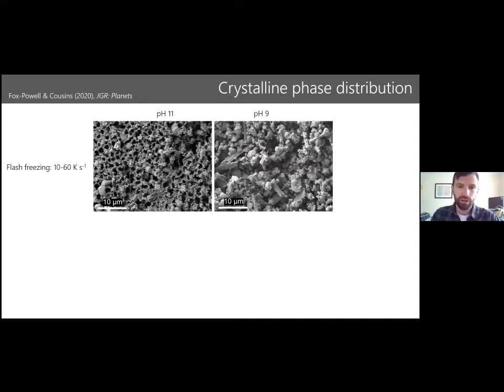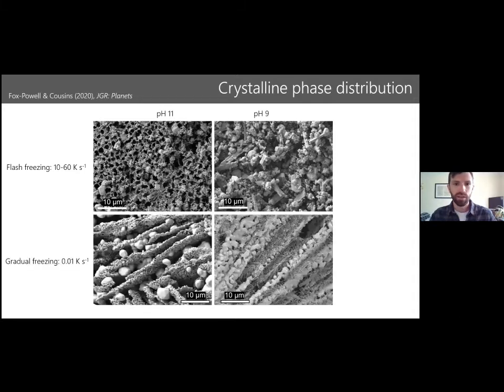So we can look at partitioning within the crystalline material itself. Now we're looking at the sub-brine vein scale. We're looking at the crystalline material partitioning within the brine veins. We did this by extracting this material via full sublimation. So we got rid of all of the ice through sublimation, and we're left behind with just this salt skeleton, as you can think about it, from the droplet. Under flash freezing conditions, this material, again, has been rewarmed from glass and has crystallized. It has a homogeneous distribution at the 10 micron scale. That's in contrast to this control experiment, which was cooled at a much slower cooling rate, about 0.01 Kelvin per second, which has formed linear repetitive structures that are really heterogeneous at the 10 micron scale.